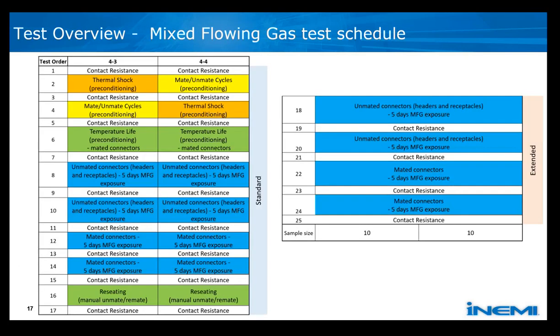Next slide, Mark, please. So following the example of the SP3 socket, this is what the test schedule looks like. It's a little complicated because it's so long, so it's divided into two parts, reading left to right. Tests 1 through 17 represent a typical standard qualification type test for the mixed flowing gas corrosion sequence, where there's some preconditioning, often a few cycles of mating and unmating, then with or without temperature life preconditioning. In this case, we added the thermal shock preconditioning. And what we did is we created two test groups. We changed the order two times to see what the order or the change of preconditioning may elicit in the final analysis.